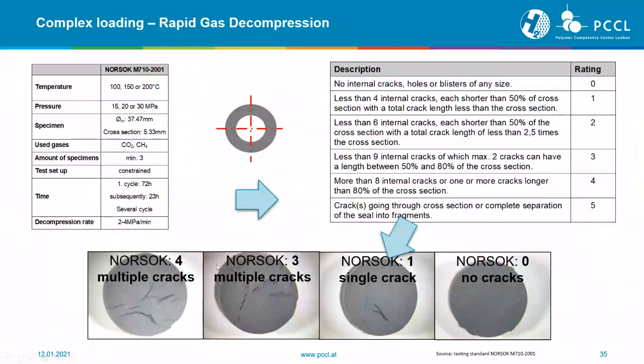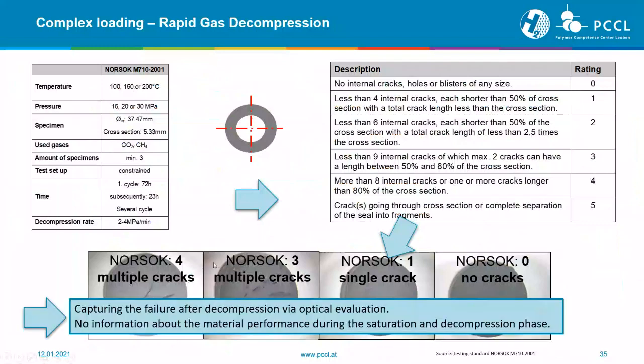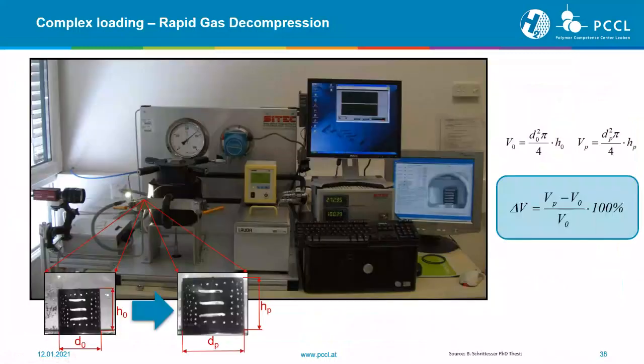What we have done in this case, or so far, is that based on the testing standard, we can just observe the material behavior after the test in terms of fracture. And we'd like to go here a little bit more into detail. Therefore, we developed together with a company partner a test setup, an autoclave test system with a camera system, where we can directly measure the volume change during the compression phase as well as during the decompression phase.